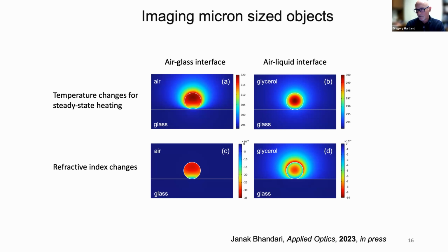It's the difference, the photothermal signal is sort of the difference between the heated and the unheated case, and so you're looking at the changes in the refractive index. So because the changes in refractive index are only localized in the bead, you know, the effects that are outside the bead basically cancel out. And so when you look at the photothermal measurement, you only see rings that are within the physical size of the bead.